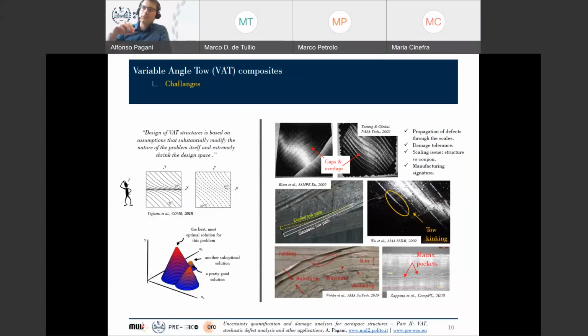So as you may imagine, steering brittle fibers, because we are talking about carbon fibers, we are talking about glass fibers, so brittle materials. Well, steering brittle fibers is not easy, because you need to do this process at the correct temperature, with the correct curvature radius. You need to preserve temperature and pressure and so on. This is rarely controlled over an additive manufacturing process. As a consequence, you will have a lot of unexpected defects. So in the right part of these slides, you see that some of the defects which are well documented in the literature. So you may have gaps and overlaps between fiber depositions. You may have a geodesic flow path or curved tow path. You may have tow kinking and so on.